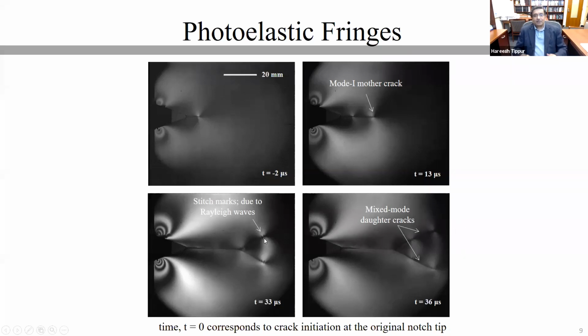One of the points that I want to emphasize here is those tiny fringes that are traveling along the crack faces themselves. These are caused by the Rayleigh waves that are propagating along the crack faces that produce contact stresses along the, because it's a nano scale crack opening displacement. So these stitch marks are attributed to Rayleigh waves that you see, but these are not necessarily the crack tip